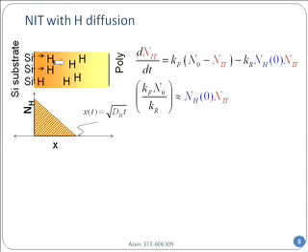Okay. Now of course, once they are broken, the hydrogen is broken, they will be walking around. Some of them will be going away, diffusing to the right and going away. Some of them will come back and see that there is a dangling silicon bond sitting there, and it will come back and anneal that bond, because it is around and there is a dangling bond, so it can just do the original forming gas anneal. It can again do the passivation. So that's the second term on the right of the first equation.